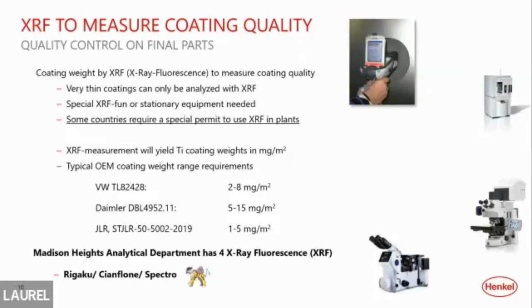Because if you get too high of a coating weight, they are concerned about welding interruption. That is one of the reasons why they want the lower coating weights. Now, this product does not have the additional polymers in it that can interrupt your welding. We do have other products where, if you need more corrosion protection, you can add zirconium and polymers and build up your coating weights. But this is primarily for a transportation coating, just to get you from point A to point B.